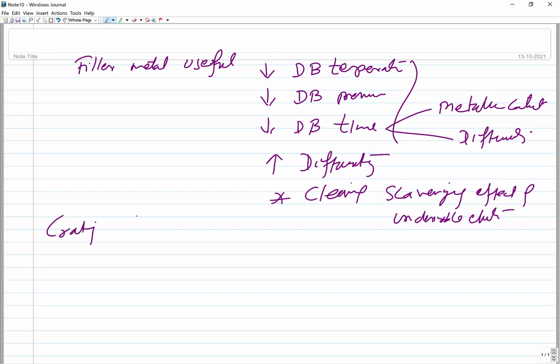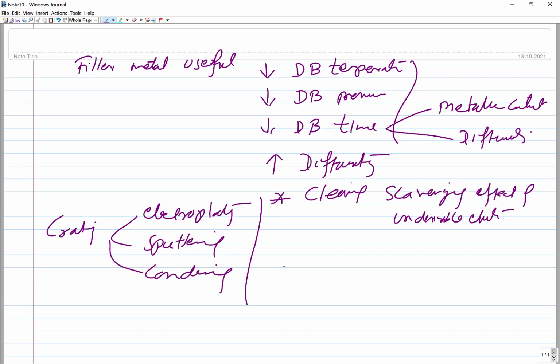So if a coating is to be developed, usually electroplating is one of the methods, sputtering is another method, or condensing the element onto the surface. And usually these are thin. Actually, this thickness is less than 0.25 mm, that is, less than 250 micrometers. It is always preferred that these are thinner ones. Just as an example, beryllium is added at the interface when developing the diffusion bond of nickel alloy. So this beryllium acts as a diffusion accelerator, which in turn helps in reducing the diffusion bonding time.